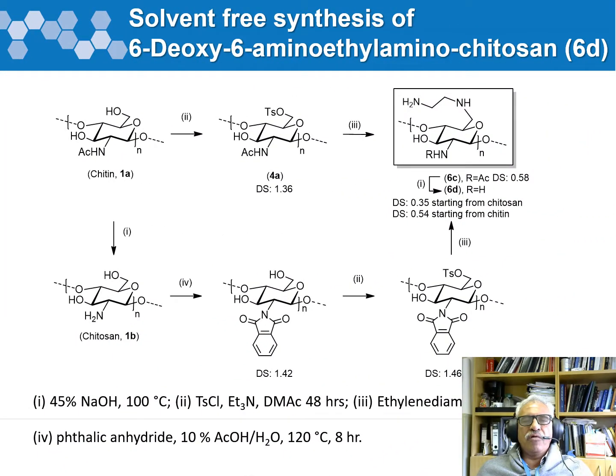So, we can also, instead of converting it to the 6-amino, use the alkylamine approach by making the tosylate, and then using ethylene diamine as a solvent and reagent. You can substitute that directly, and then of course you can remove the acetyl group, so you get a diamino but with an extended alkyl 6-amino ethyl amino extension here, which in itself is also quite water soluble. So you can either go that way, or first go to the chitosan, protect, tosylate, and then treat with ethylene diamine, and you can then deprotect your phthaloyl group, so you get your diamine or 6-deoxy 6-amino ethyl amino chitosan, which is water soluble.